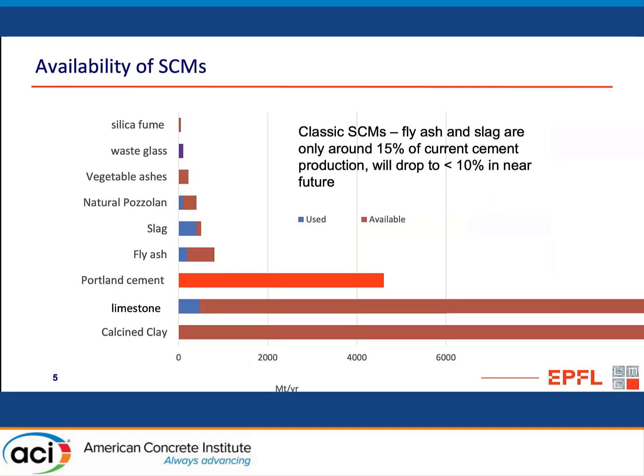So John said I was going to talk about resources, and this is probably the most important slide I have, because we talk a lot about fly ash and slag, and if we look at these materials here, you see the amount available is really quite small compared to the very, very large demand of cement. If we take slag, the amount of slag produced in the world today is about 8% of the demand for cement, and that's going down.